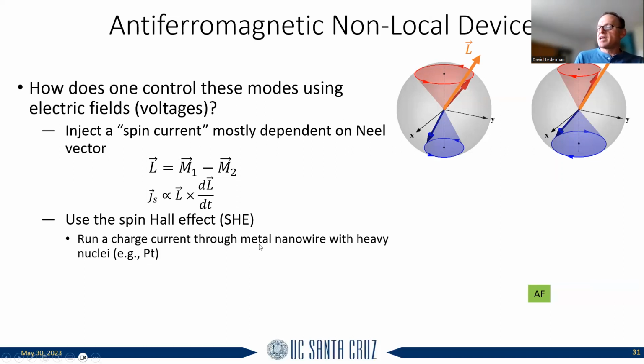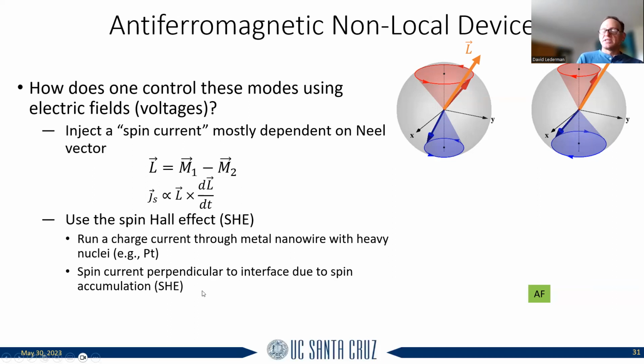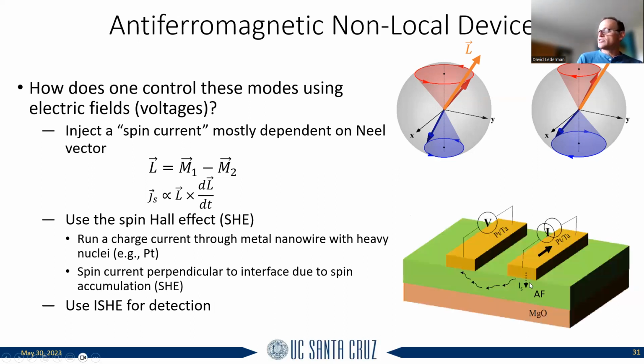So you use the spin Hall effect. You can run a charge current through a heavy metal with heavy nuclei like platinum. You can generate a spin current perpendicular to the interface due to spin accumulation, and then you use the inverse spin Hall effect for detection. So it looks something like this. This would be a device where you could create magnons. You could get magnetic excitations going from right to left here by running a current through here, because you get spin accumulation due to the spin Hall effect in the platinum.